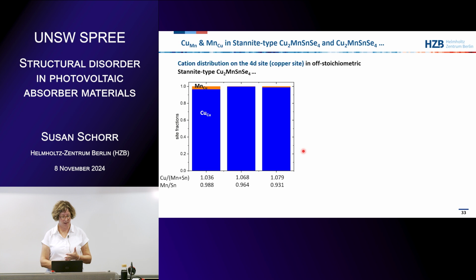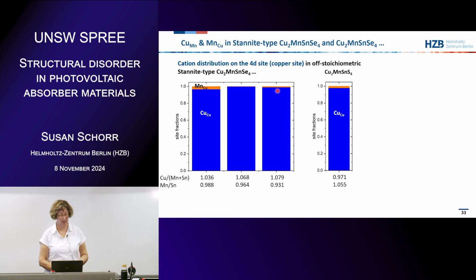So the question was, if we have copper manganese disorder, that means, do we see copper on manganese and manganese on copper antisites? This is just for the 4d site, which is the copper side, so this copper plane. This is for 3 different samples of copper manganese tin selenide with different stoichiometries. These are the cation ratios here. And you see there is not much manganese on copper in these 3 samples. Also in the sulfide, so this is a stoichiometric copper manganese tin sulfide, there is also not much manganese on copper.